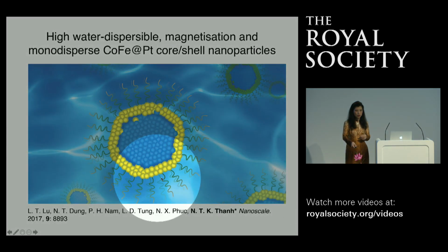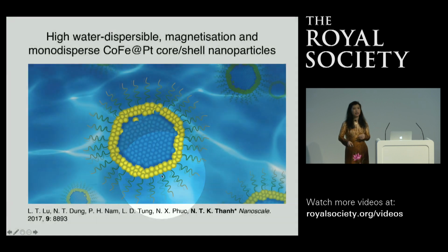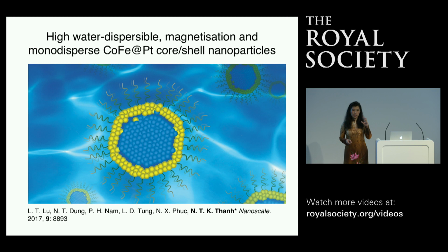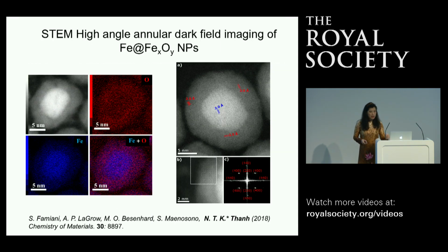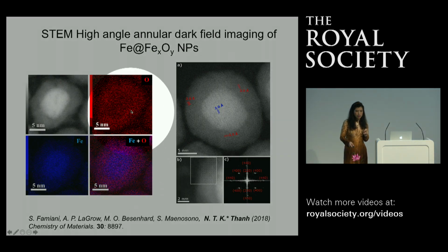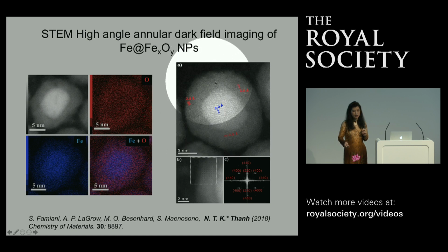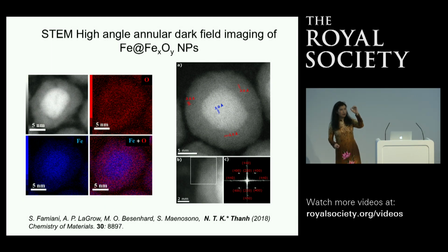But we need to have a coating, and this coating is platinum, because platinum is inert, a bit like gold. And then we need to disperse those nanoparticles. Then we didn't give up the aim of making iron. Remember that zero-valent iron is so difficult, it bursts into flame. So the way we made them, we know we couldn't make the pure iron, but we got a little layer of iron oxide. And it turned out that when it reached 4 nanometers, it doesn't get oxidized any further. So the key is, now you make the whole thing bigger, then you get a bigger core, and you're going to have a bigger magnetic moment of your nanoparticle.